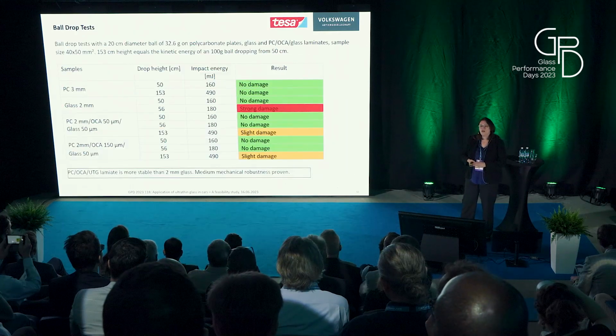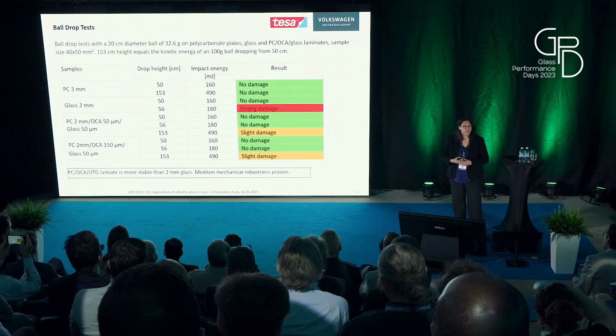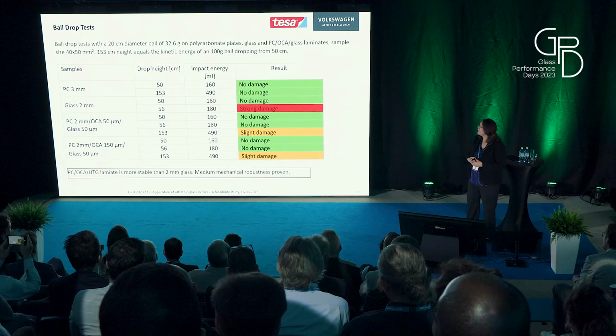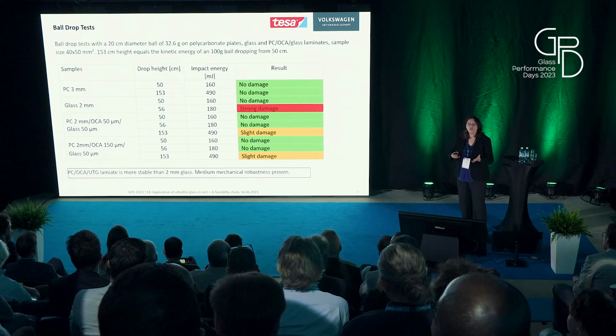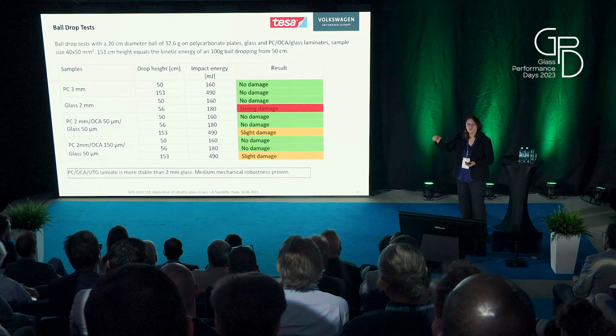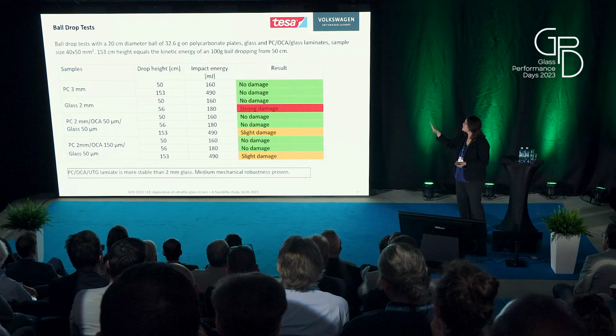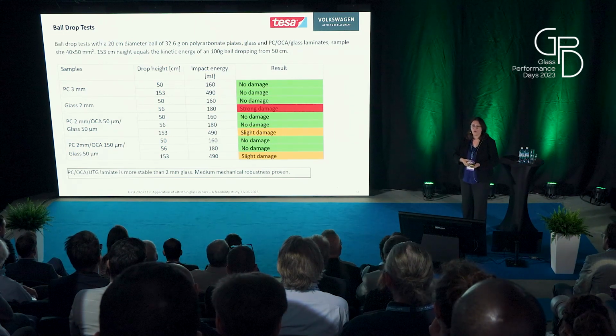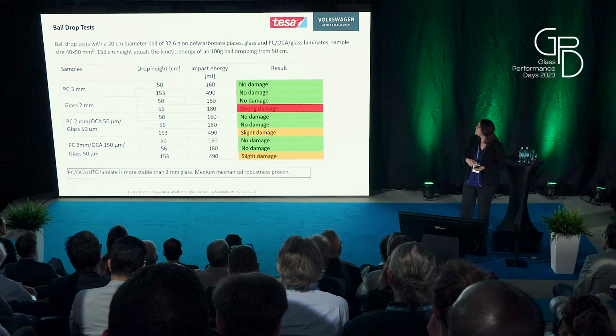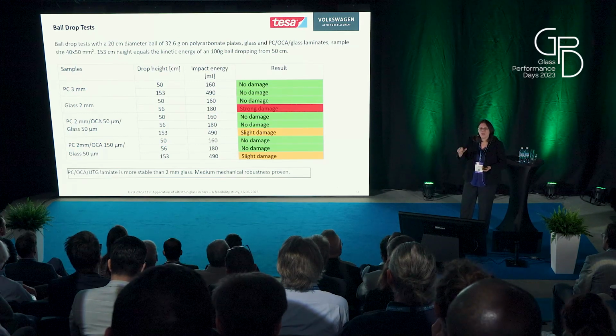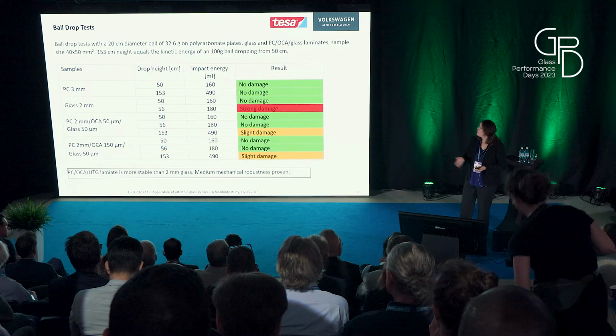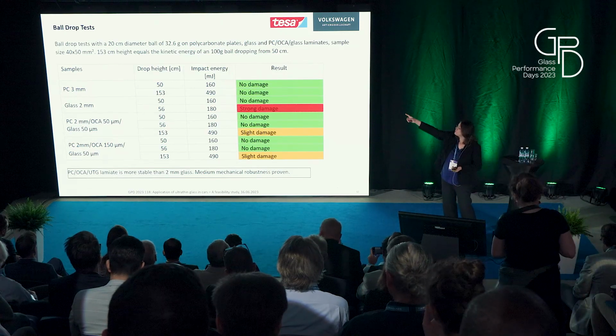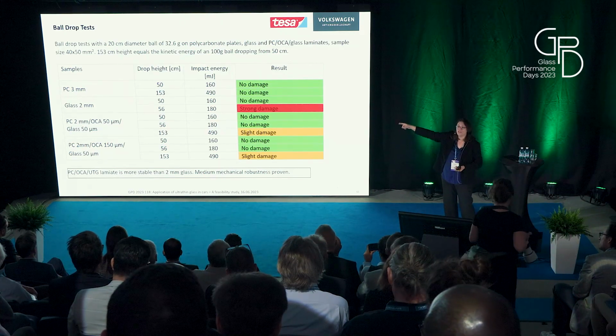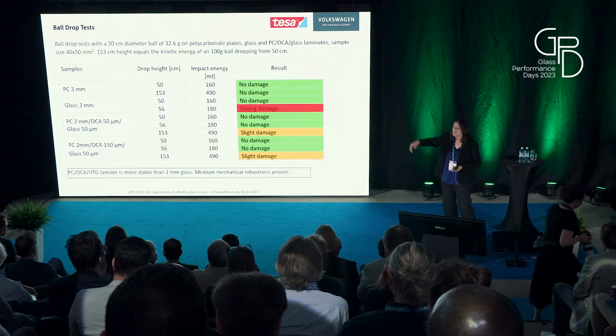All right. Now let's go to the application of B-pillar. Here we thought, okay, what is a good value? There's no standard test in finding out what about pressure and so on. So we just thought, okay, we take a 100-gram ball, let it drop 50 centimeters. That might be a good rule of thumb. But we didn't have a 100-gram ball, so we took a smaller one. That's why we have these uneven numbers here.